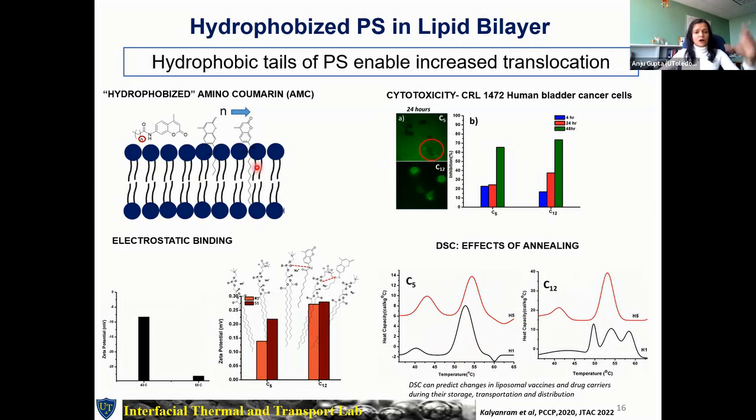However, when you have a long chain, what you see is phase separating domains. So in the first cycle, while C12 was going in deeper, it created a lot of disturbance within the lipid bilayer. Now you have some DPPC rich domains, some DPPS rich domains, and some mixed domains.